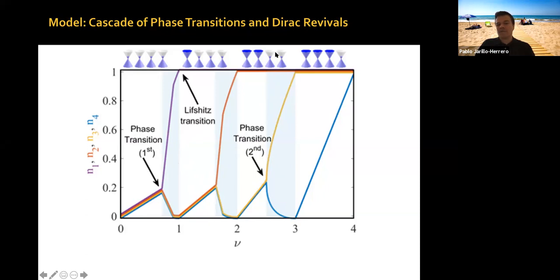When it is about to reach half of each of these flavors, the system again decides to spontaneously break the symmetry and fill one flavor, then go to charge neutrality, and then the last flavor is filled. So this inverse compressibility study, and our collaboration with the theory colleagues, was really very insightful, because it provided insight into something that we had already seen in our original transport experiments, and that has also been reproduced by many others, which is that the ground state of your system is very different when you dope with density. As you vary your filling factor, right before you reach the correlated insulator states and right after, the ground state of your system is very different.